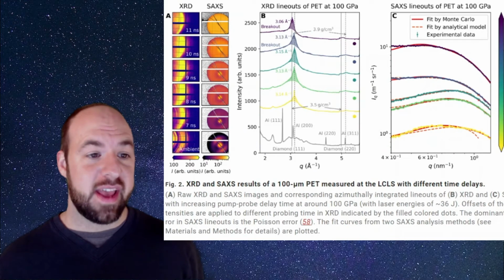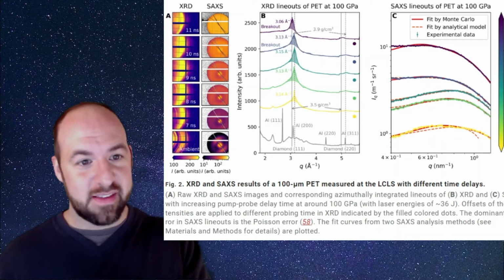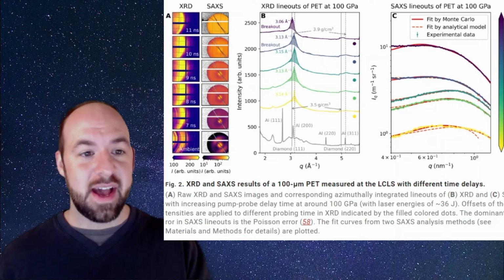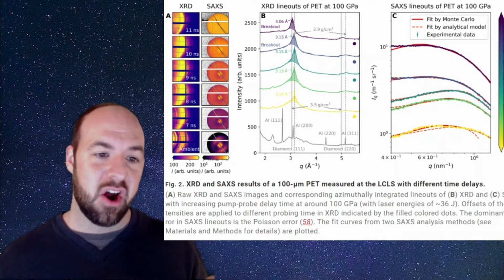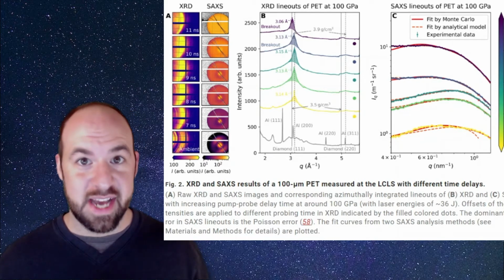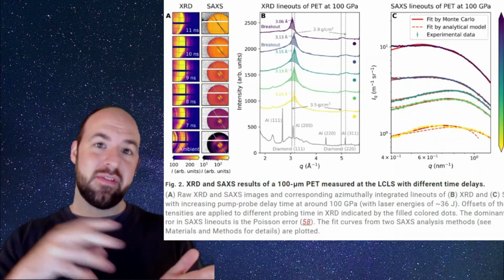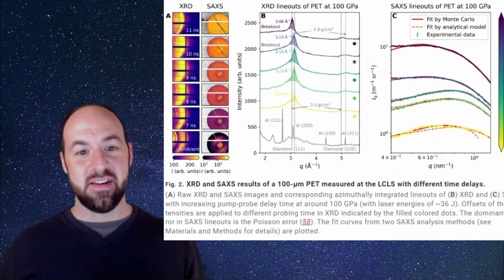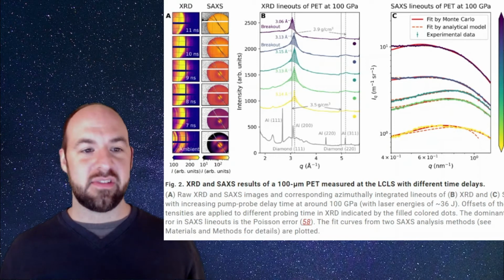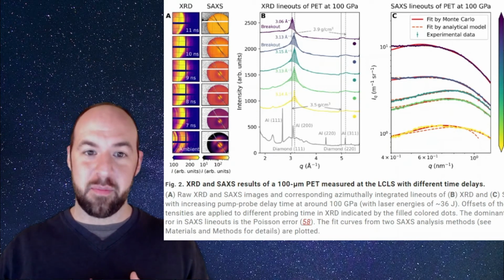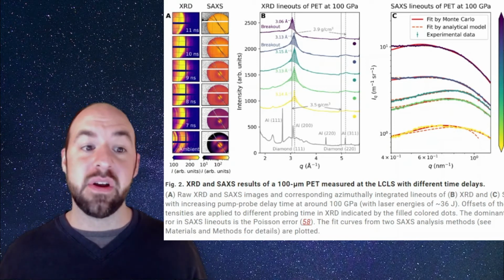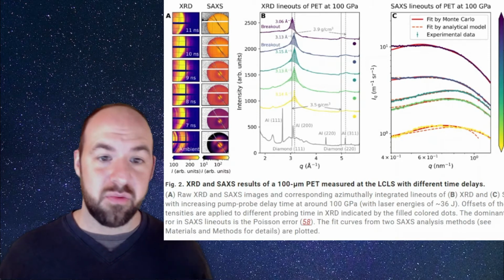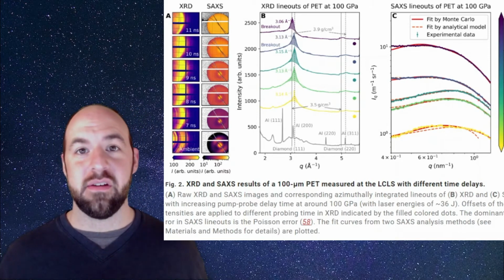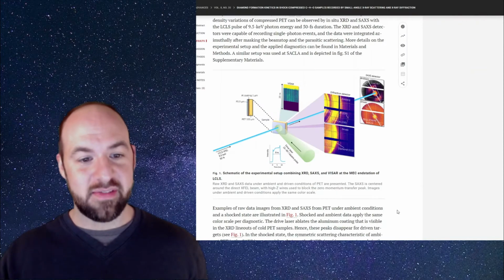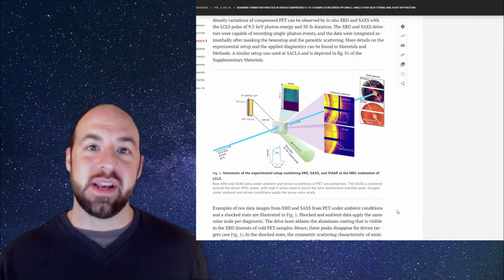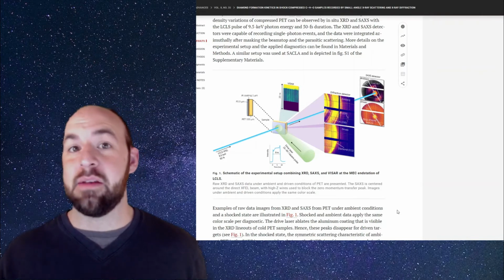And in figure 2, they start to analyze it, and basically there's a lot of science going on here. But what they're finding out is, thanks to the X-ray diffraction, they are observing that there's actually diamond being formed as they pulse the plastic with a laser. And meanwhile, the small angle X-ray scattering is giving them a sense of the particle size of the diamonds. And the diamonds are very, very small. They're about 3 nanometers or so, 2 or 3 nanometers. And what they're finding is as they pulse the plastic with a laser, it is forming nanodiamonds in real time. That's the main result of the experiment.